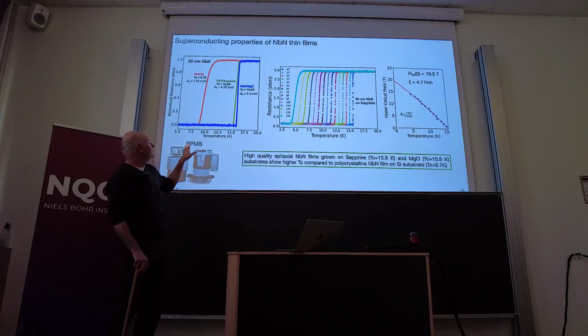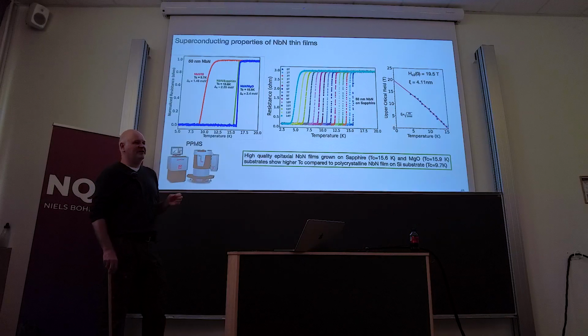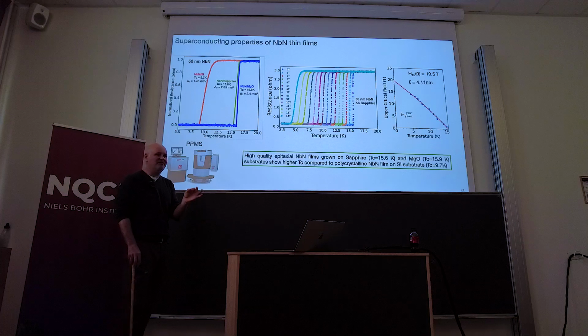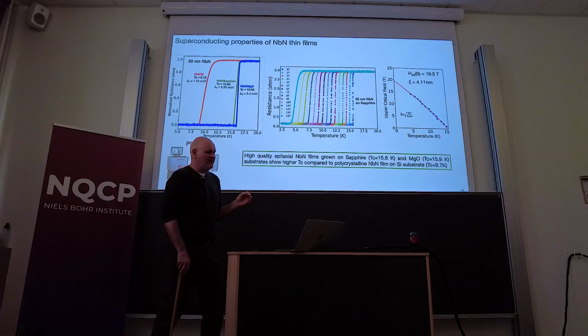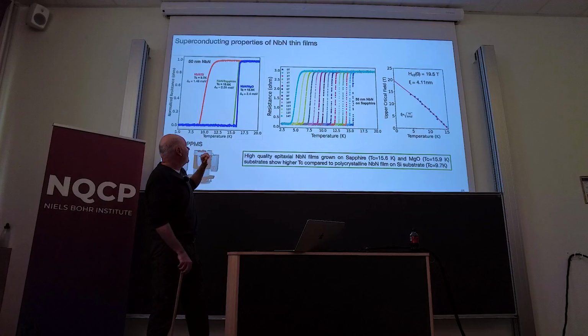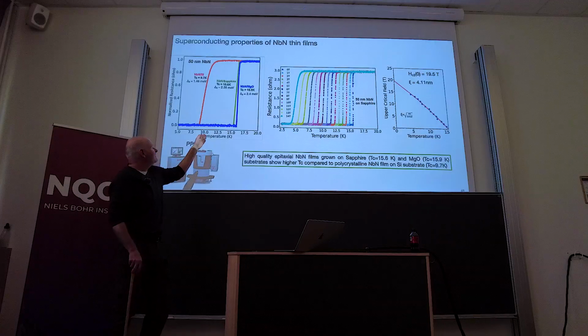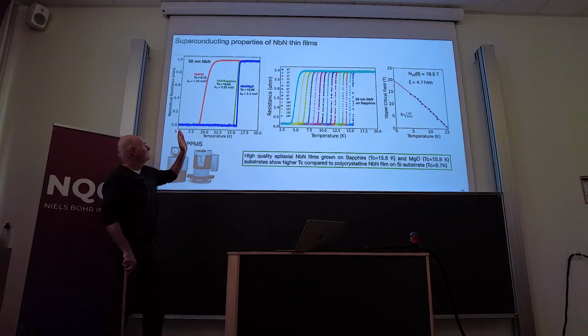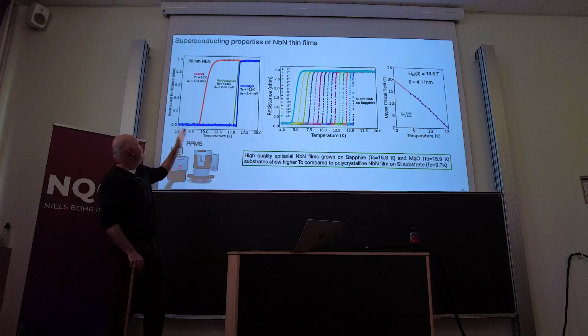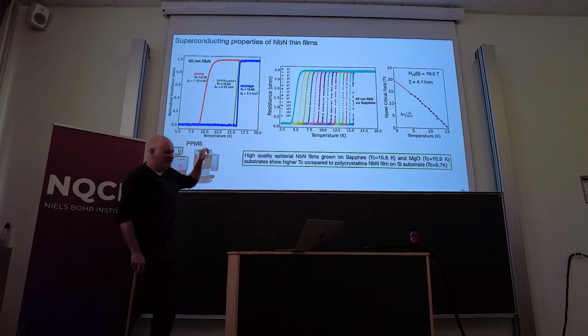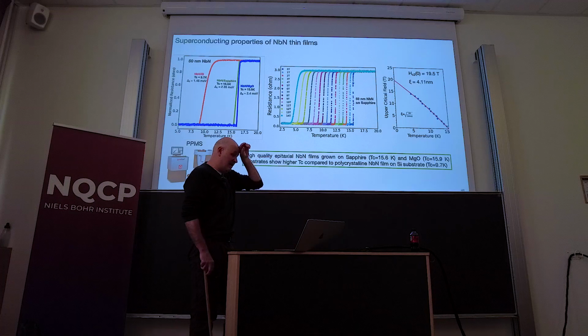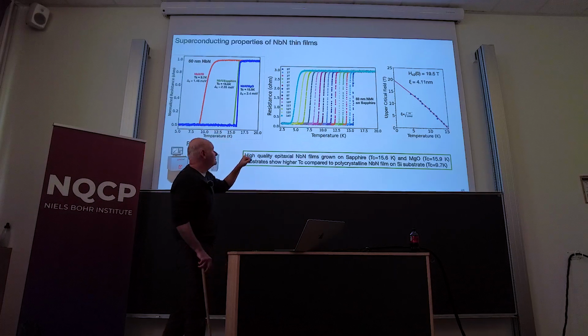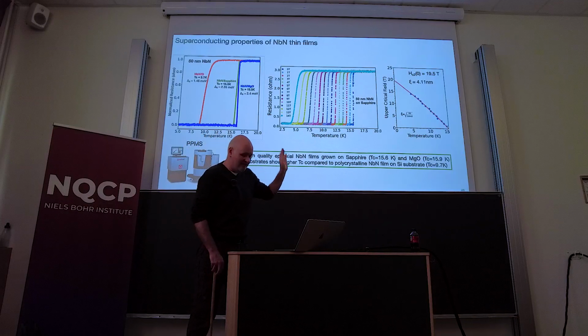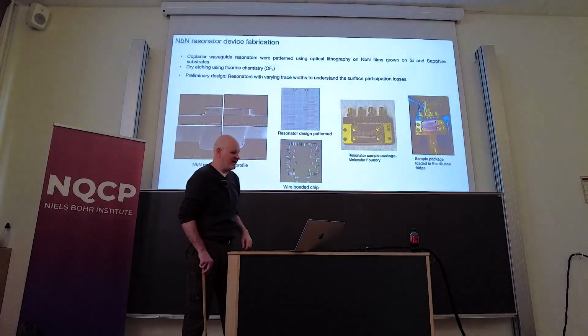So then we take these films, load them into our PPMS, which for those of you who don't know is essentially a very, very small stage cryostat that cools down very quickly, and run TC measurements on them. And you can see that the TC of the films is well correlated to essentially how high a quality the crystal is. So magnesium oxide has the highest crystallinity, and also the highest TC. Silicon, lowest crystallinity, lowest TC, and the transition width correlates as well. We also did magnetic field measurements to get critical field. So essentially we map out the entire space.